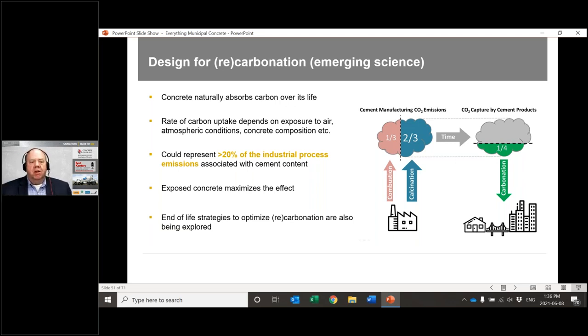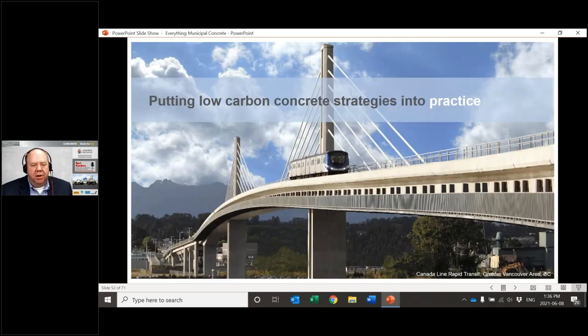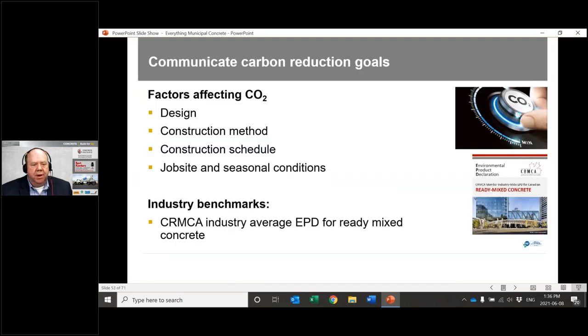But for things like curb and sidewalk, when we're done with their service life, let's say they're 30, 40, 50 years old, and we're ripping them out, we can crush that material. When we crush the material, we give it a very large surface area, and we can use that granular material either back in concrete or as a granular base for new construction. And if you're using it on a granular base, then you've got maximum surface area to absorb CO2 again. So again, we're seeing a lot of research into what we can do there.